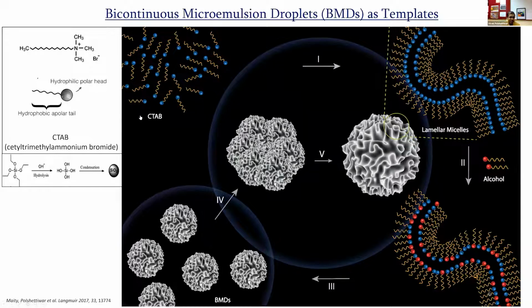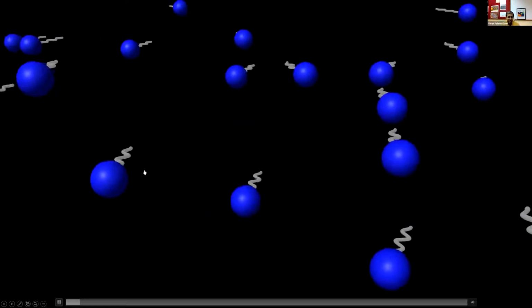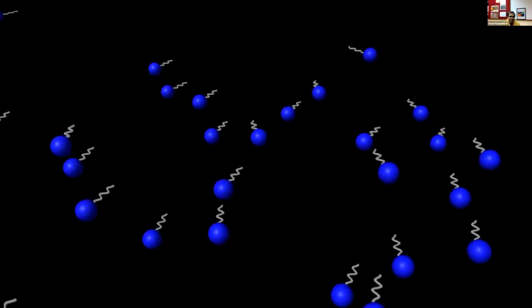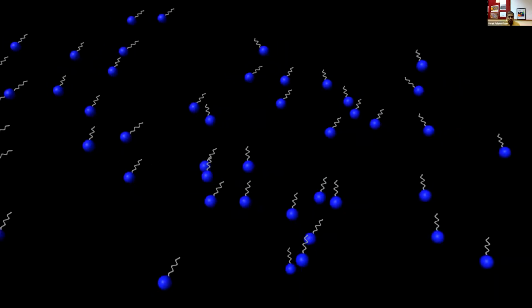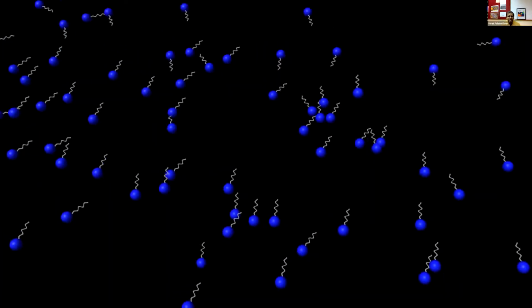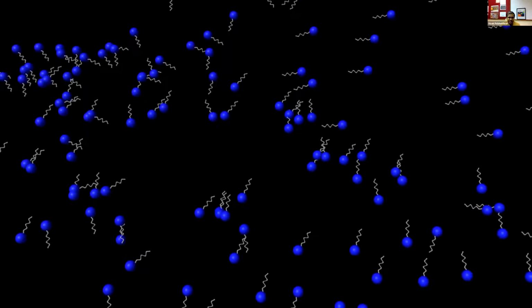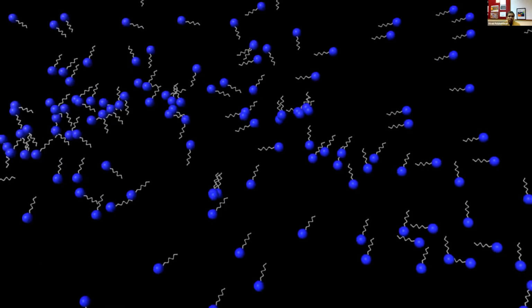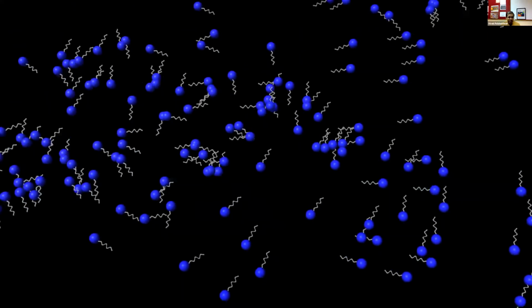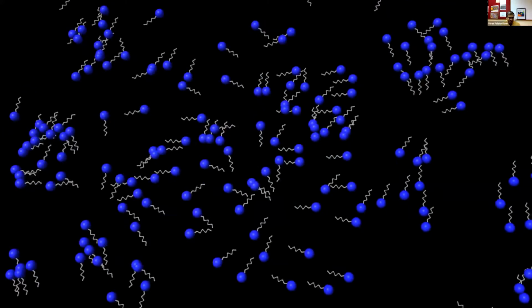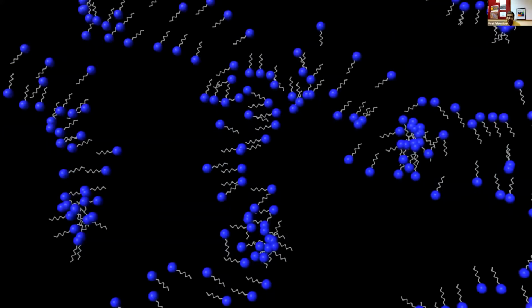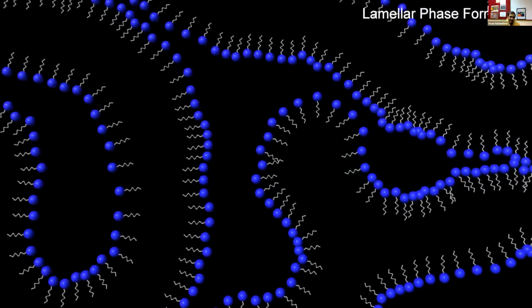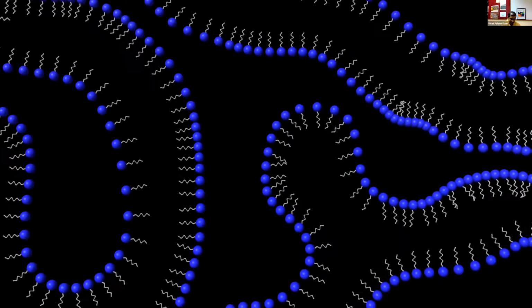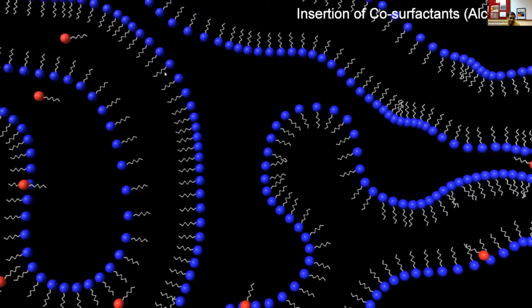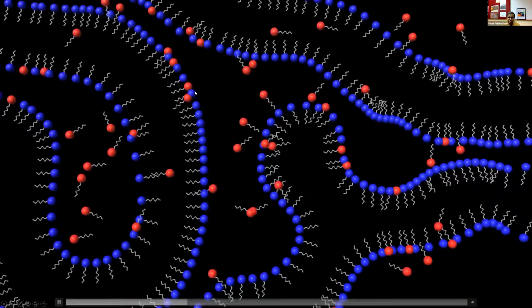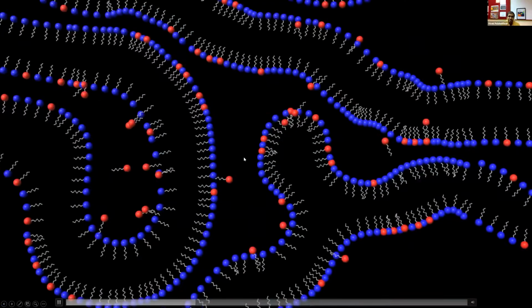So these are the template molecules. The blue ball is the quaternary nitrogen, and the zigzag line is the hydrophobic C16 chain. Now we add them into a solvent which is a mixture of xylene and water, so polar and non-polar, and the concentration of these molecules is such that they form a random lamellar phase. And then we added one more co-surfactant, pentanol or hexanol, which stabilizes these interfaces by minimizing the repulsion between the quaternary nitrogens.